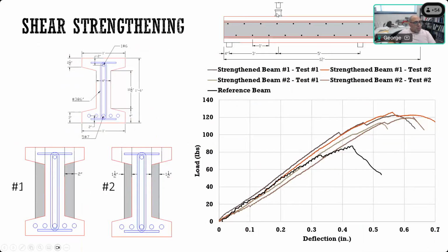We actually tested 5 girders. The first one, the black line, is the one before strengthening, and then we had 2 strengthened using 1.5 inch additional web, and the other 2 for 2 inches, and you can see a significant increase in the shear capacity by adding only 1.5 inches or 2 inches of UHPC around the web. And we didn't notice any kind of delamination or separation between the 2 materials. So that was a very successful application.